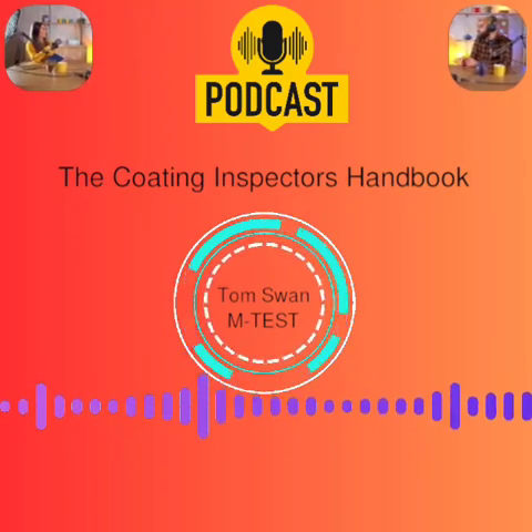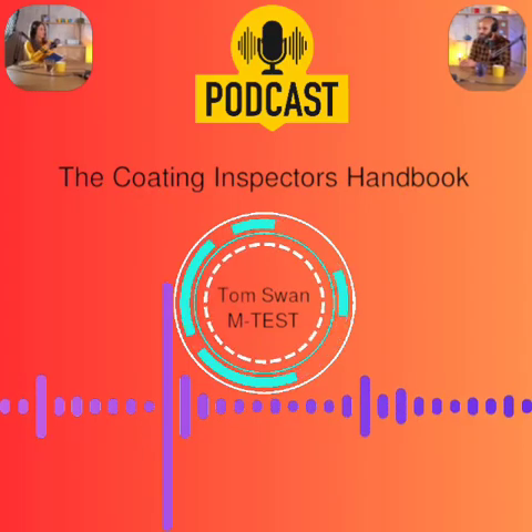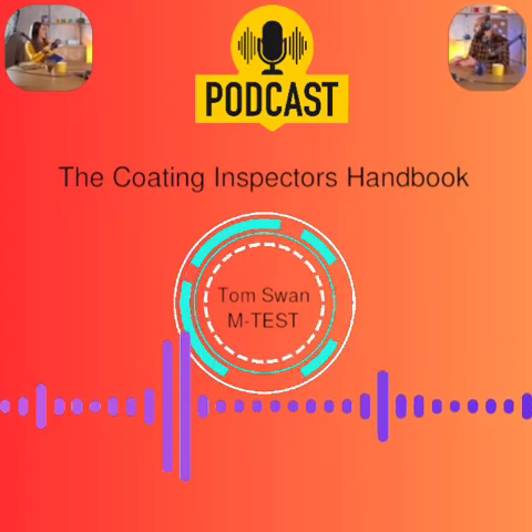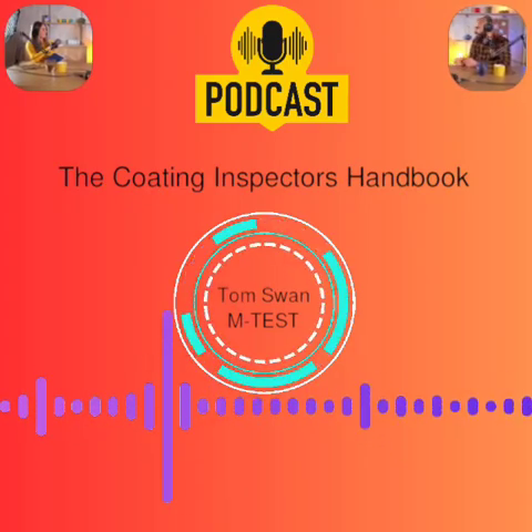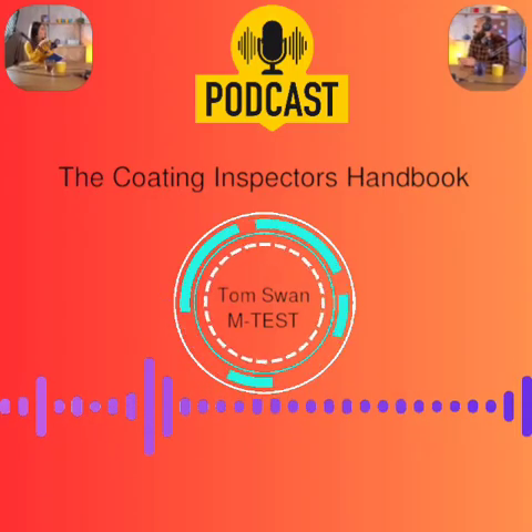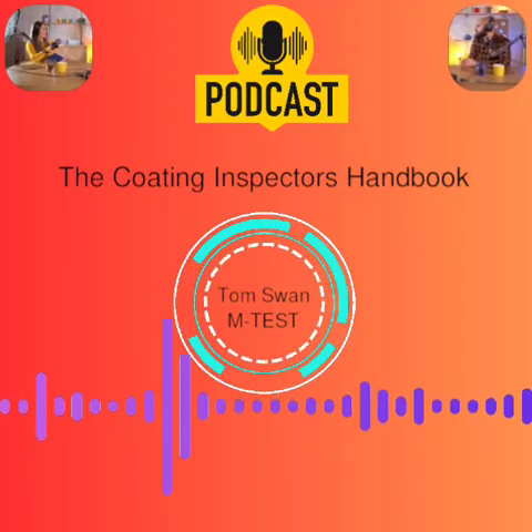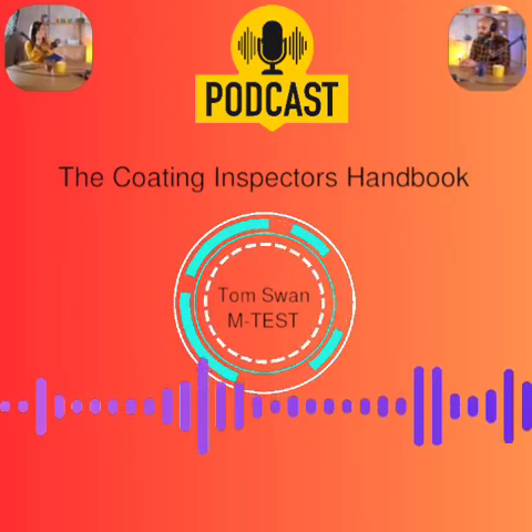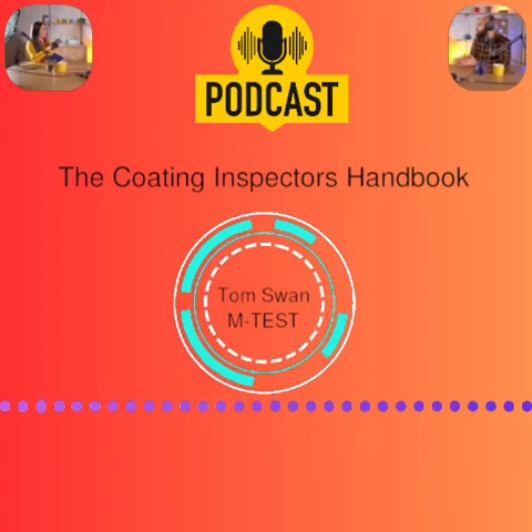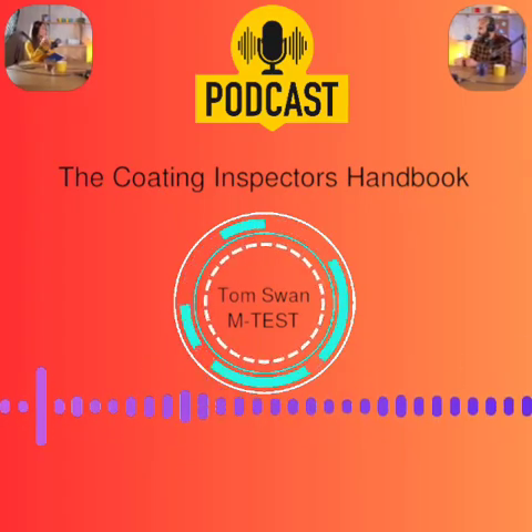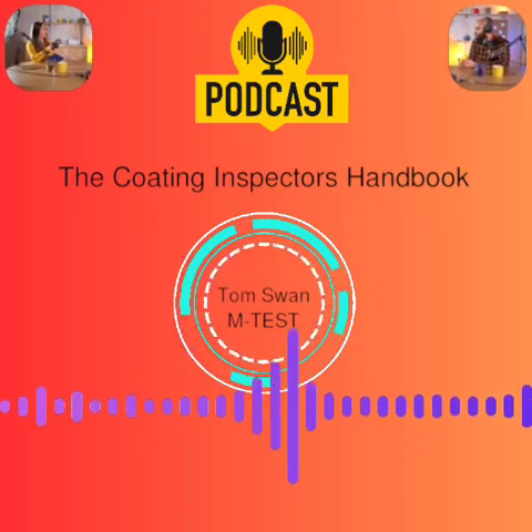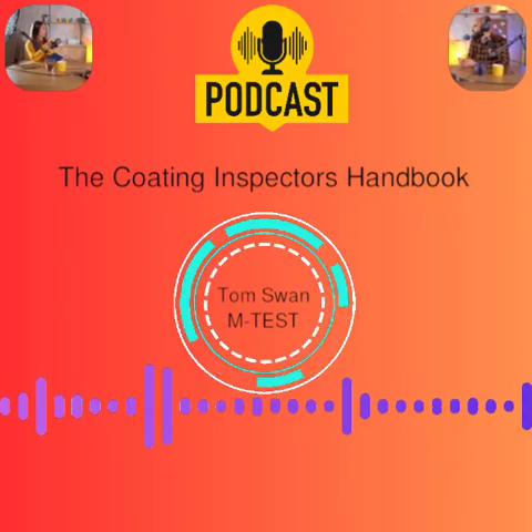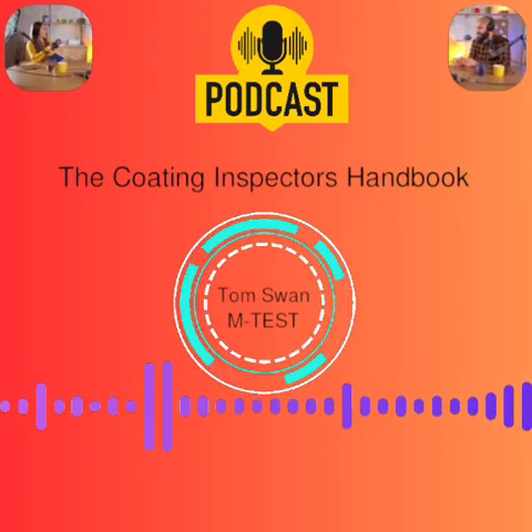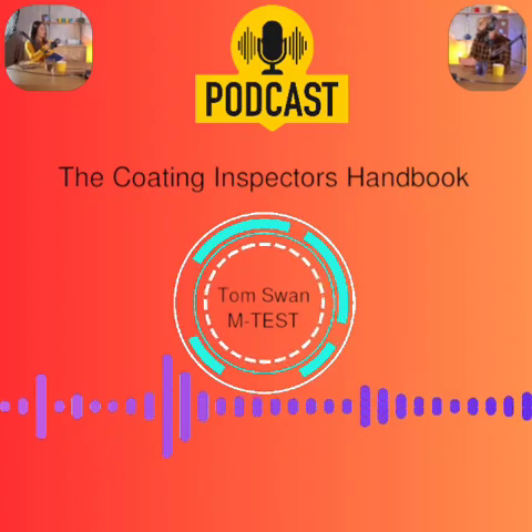Let's circle back to BMR, base metal reading. Handbook says it's misunderstood. It really is, especially critical for thin coats. BMR is the reading you get on the bare, uncoated profiled substrate. Affected by steel's magnetic properties and the surface profile itself. The gauge establishes 0 based on the magnetic field. On a rough surface, that 0 is effectively averaged somewhere above the peaks. So the valleys are below 0. Exactly. The meter won't show any reading until the paint is thicker than that BMR offset.